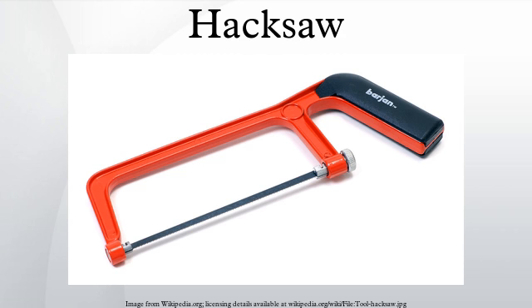life. These blades were first available in the all-hard form, which cut accurately but were extremely brittle. This limited their practical use to bench work on a workpiece that was firmly clamped in a vise. A softer form of high-speed steel blade was also available, which wore well and resisted breakage, but was less stiff and so less accurate for precise sawing. Since the 1980s, bi-metal blades have been used to give the advantages of both forms, without risk of breakage. A strip of high-speed steel along the tooth edge is electron beam welded to a softer spine. As the price of these has dropped to be comparable with the older blades, their use is now almost universal.